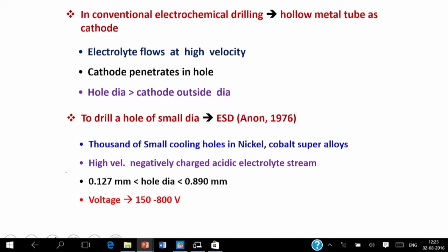But in electrostream drilling, an acidic electrolyte is used. So whatever debris particles and metallic hydroxides are generated dissolve into the acidic electrolyte. As they dissolve, they do not clog the inter-electrode gap, so you can generate any kind of hole of any dimension. Using electrostream drilling, thousands of small holes can be made in nickel, cobalt and superalloys. A high velocity stream of negatively charged acidic electrolyte is used, the hole diameters generated are 0.127 to 0.89 millimeter, and the voltage applied is 150 to 800 volts.